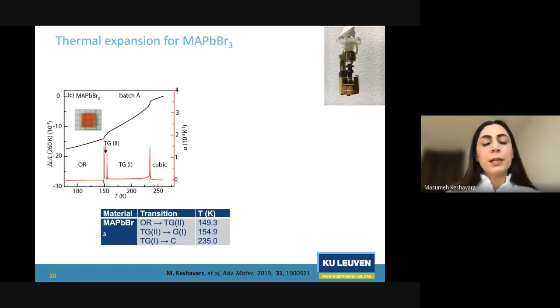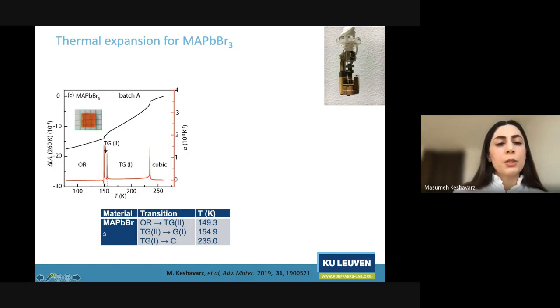So if we now replace the iodide with bromide, we see a more complex transition scheme, and we see that at room temperature it is cubic. Then there is a transition from cubic to tetragonal. Also, it is known for methylammonium lead bromide that in the tetragonal phase, the different directionality of the MA group can induce a little bit of change in the tetragonal structure, named tetragonal 1 and 2. This has never been seen via XRD, or X-ray diffraction methods, but this method, thermal expansion, is so sensitive that one can observe such little changes in the structure. So we were happy to see that, and then later on it goes from tetragonal to orthorhombic.